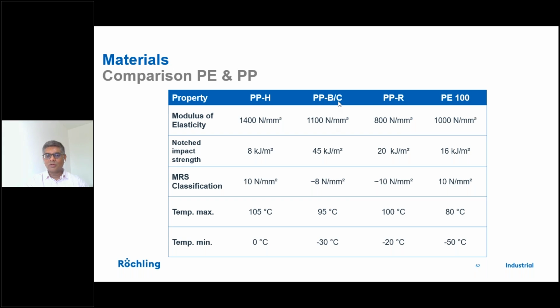As I mentioned, when you need properties of impact and low temperature, then you need to go for PPB. But again, you will see here some analysis about the impact, the MRS class, and the operating temperature. But the best way would be to talk to us or write to us, so that we can give exact feedback on which is the best material. See here, for building rectangular tanks, pickling tanks or plating tanks, PPH is one of the best materials, because it has the highest mechanical strength, 1400 megapascal, whereas everything else is less. So this also becomes one of the most economical materials to use, and the best. So this is the optimum material. The rest are all case-to-case requirements of the material.